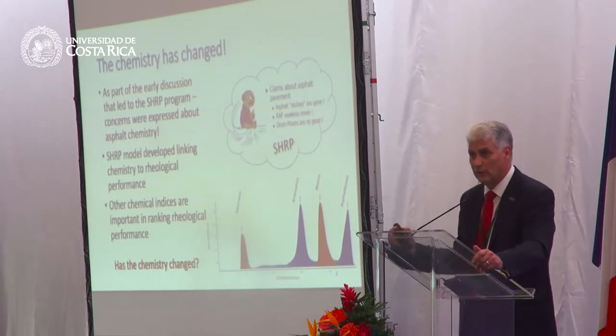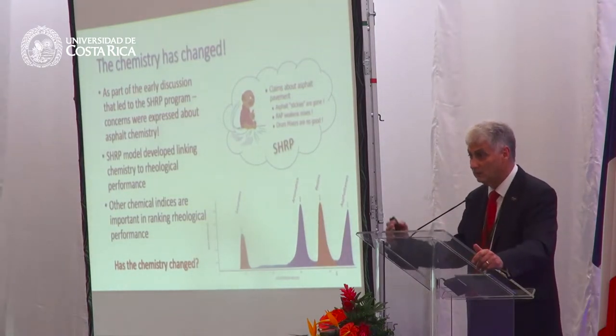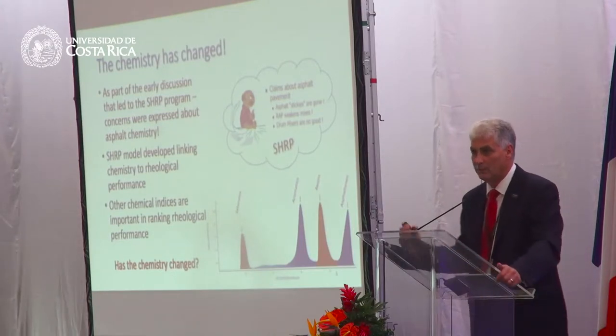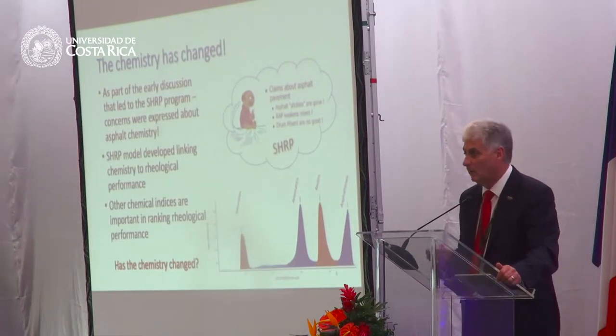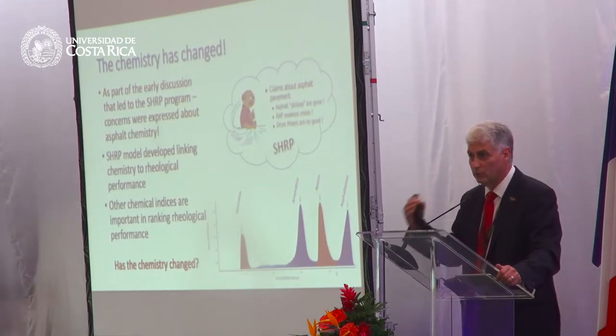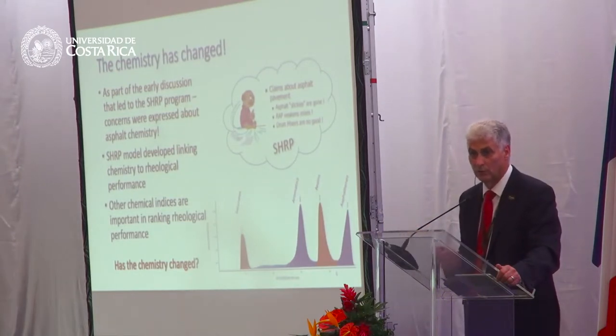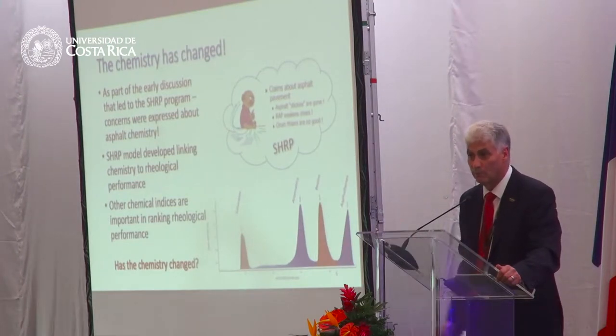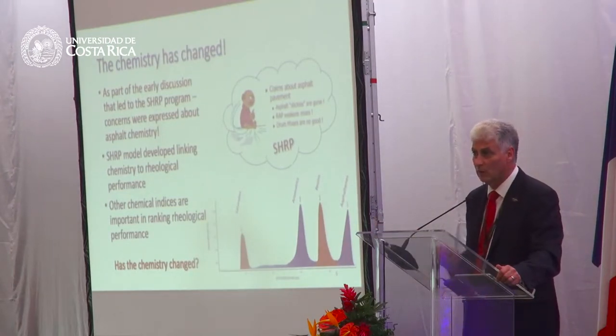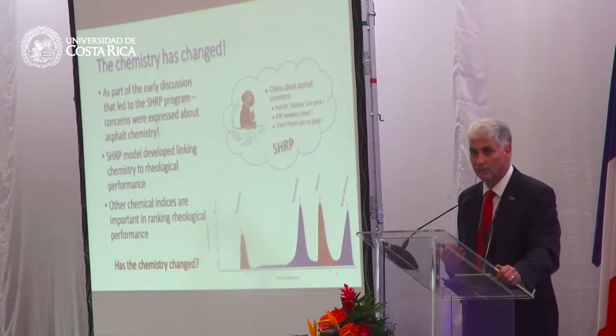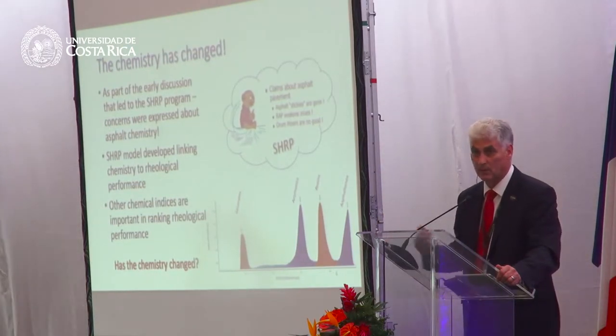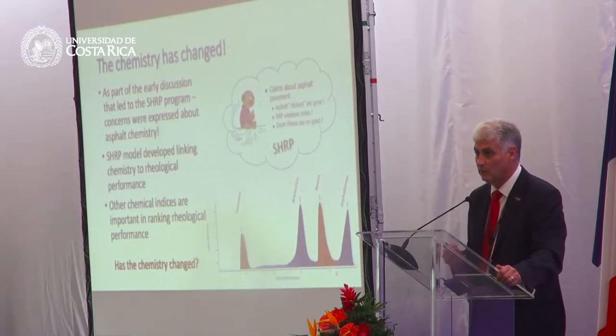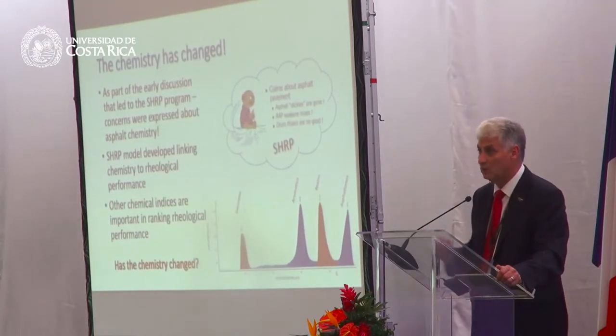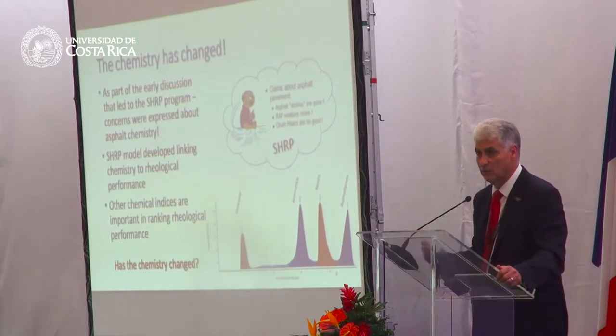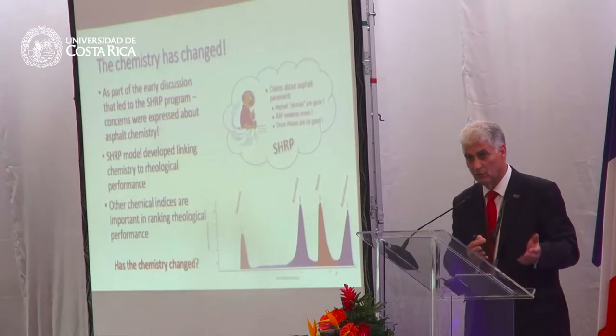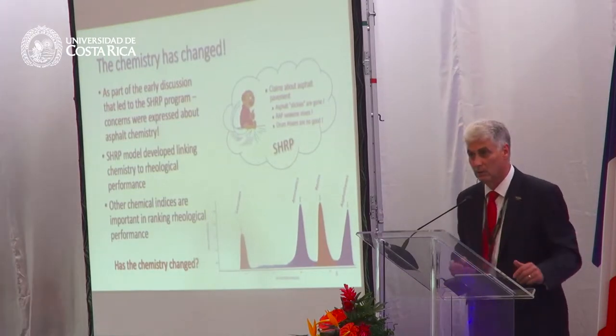However, if you look at the changes in chemistry today, they are significant changes. We have the implementation of mega refineries, and the mega refineries produce virtually no bitumen. The residual content coming out of those refineries is on average 1%, whereas the classic old-style refineries, the residual contents coming out of those are in the range of 10 to 20%. So this means that the asphalt that we're using today, or the bitumen, has changed in terms of how we see the chemistry today to what existed during the original SHRP research work and what we were using 20, 30 years ago.